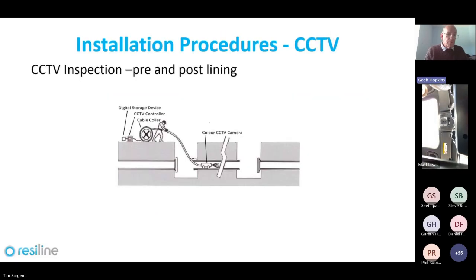So after you've cleaned the pipe, you carry out a CCTV inspection when you consider the pipe is fully cleaned and immediately before the lining process commences. You're trying to obtain a record of the pipe as it is when you line it. You don't want a CCTV survey from the day before or something like that, because who knows what's happened in that pipe overnight. So CCTV is carried out immediately before the lining process commences. Next slide, please, Tim.